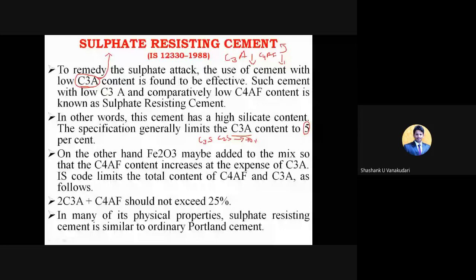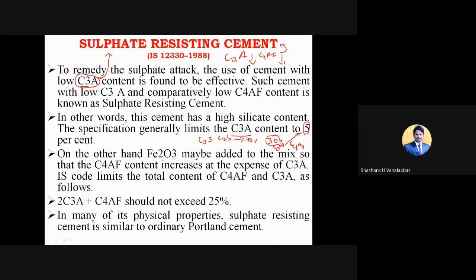Okay. So now the remaining 30% belongs to C3A as well as C4AF, right? In this 30%, the C3A content should be restricted to less than 5%. Then only can we consider this as sulfate resisting cement.